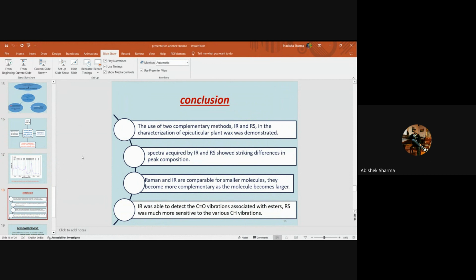And we also found out that the spectra of IR and RS have striking differences in the peak composition. We saw that IR showed much more peaks and responded well with many of the compounds present in the wax, and then Raman and IR are comparable for smaller molecules. As the molecules become bigger, the complementarity becomes more complex. Okay, so the IR was also able to detect C=O vibrations associated with esters, whereas RS was much more sensitive to CH vibrations.